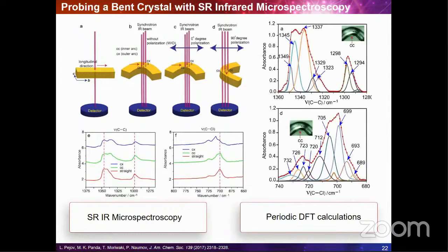And so this approach reproduces well some observed trends, such as the wall effects, and also provides estimations of the vibrational shifts, unit cell deformations, the intermolecular parameters, and so on. In general, we conclude that expansion of the lattice induces redshift, while compression induces larger blue shift of the characteristic modes. And since this approach does not include parameters related to the actual stimulus by which the deformation has been